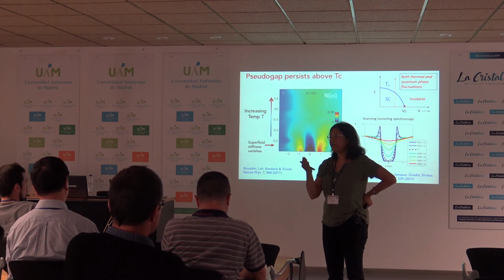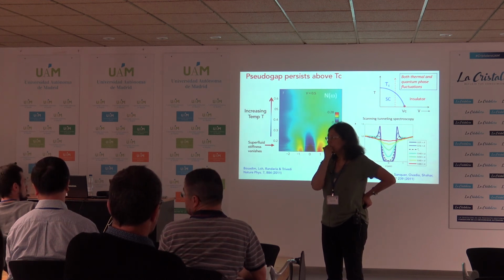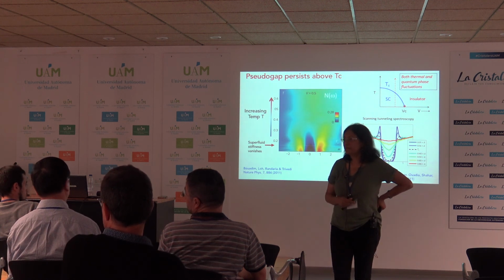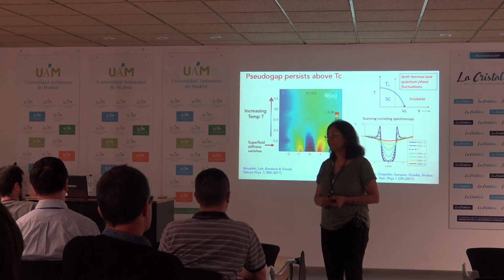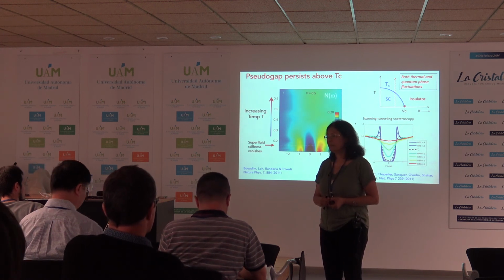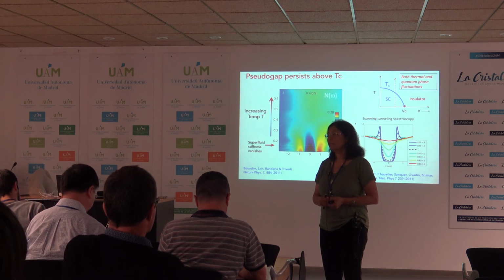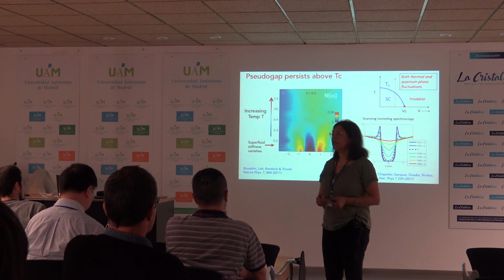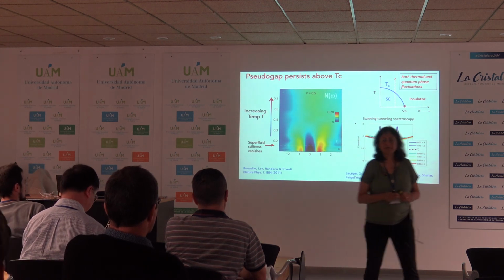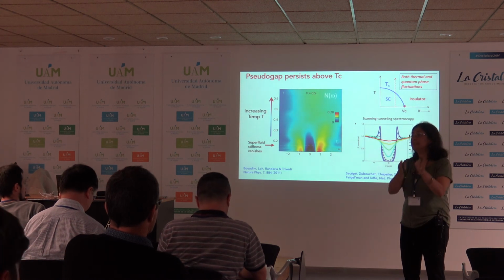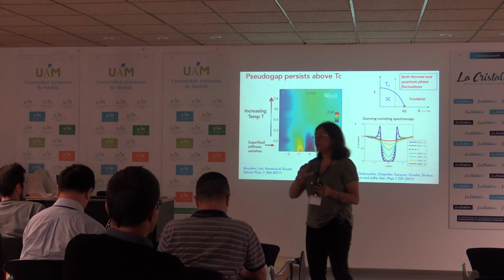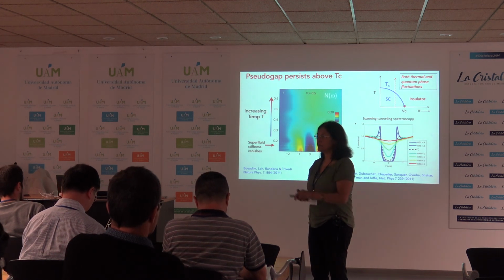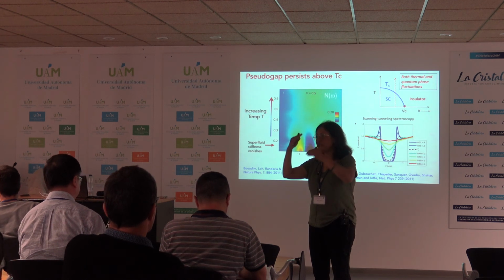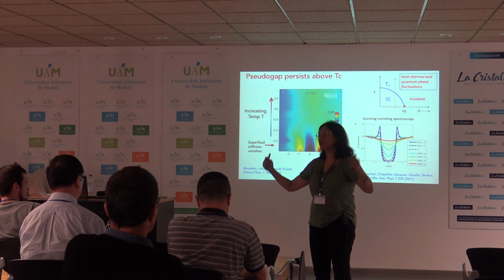That's possible. It's very much like Mott selective behavior in transition metal oxides. Some bands become Mott-like and some are itinerant. Orbitally selective. So you're saying that if the gap, related to other quantities, dominates the other quantities which are microscopic, then I could call that a pure BCS-BEC crossover system. Yeah. But it brings in the richness. You could go through multiple crossovers, right? There may just be one phase transition, but there could be multiple crossovers where single particle gaps could be switching, and then you're comparing it with an overall rho s.